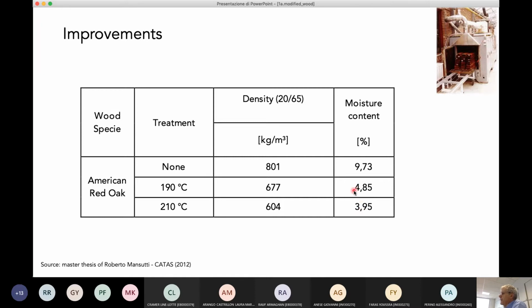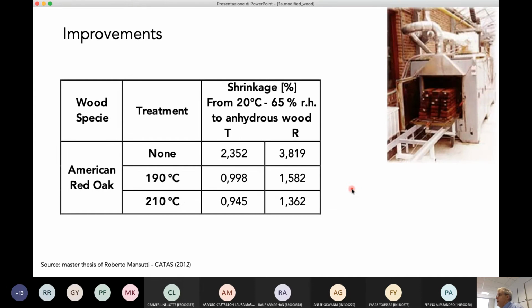So this is clear evidence that thermotreated wood is considerably less sensitive to water. Of course, also shrinkage is reduced. This is an experiment carried out here at CATAS, and Roberto calculated the shrinkage between 20 degrees and 65% humidity conditions until the moisture content was practically zero.